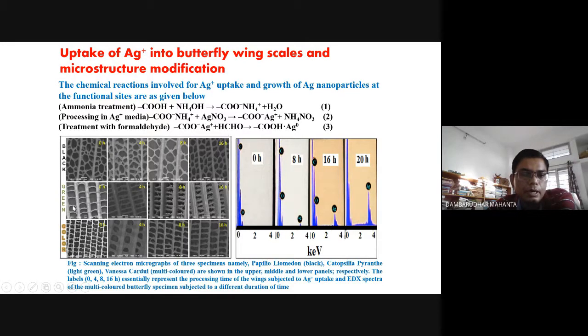In the green case, you have periodically arranged chitin surfaces having pores separated by ridges and cross ribs. In case of the colored one, you could see that there are ridges, ribs and cross ribs, and also some thorn-like structures or edge-like structures in between. So after infiltration with ammonia followed by silver and then formaldehyde, we could see that there is a change in the pores and also a swelling behavior. In the green case, you could see there are some globular-like structures, called beads, and these beads have emerged because of these treatments; they are now swollen.